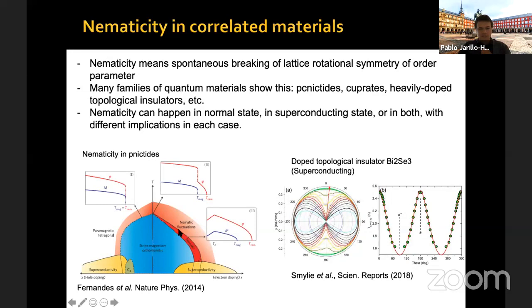where you can see that in the normal state, the system exhibits this red region, which is the nematic transition. In doped topological insulators, such as copper doped or strontium doped bismuth selenide, which is a superconductor, you can see that the resistivity of the system, or in this case TC, exhibits 2 maxima in 360 degrees, indicating that the system goes from the original hexagonal symmetry to this 2-fold symmetry. 2-fold means an ellipse, or in this case an ellipse or a peanut, but basically you have an axis of mirror symmetry. So you have 2-fold symmetry here. Now, the system has chosen a direction. Let me show you our data.